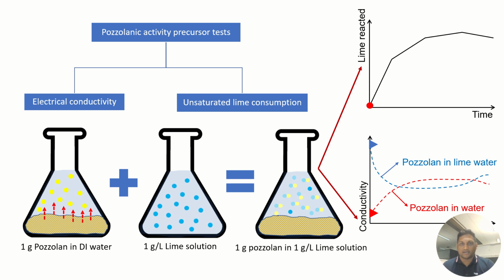We considered electrical conductivity and unsaturated lime consumption as the precursor test. The left side beaker showed the ion dissolution in DI water from the pozzolan, which increases with time. The middle one showed the dispersed calcium ion in DI water at a fixed concentration. Combination of both systems induces the hydration product formation gradually with time, and the calcium concentration reduces along with the conductivity.